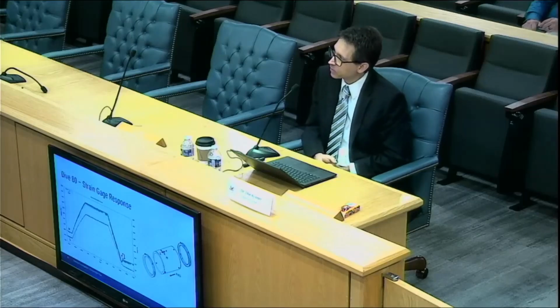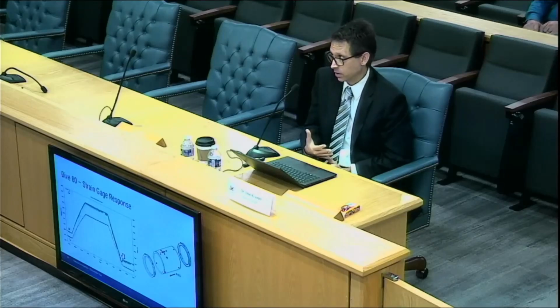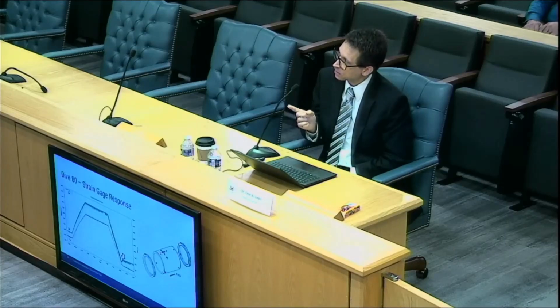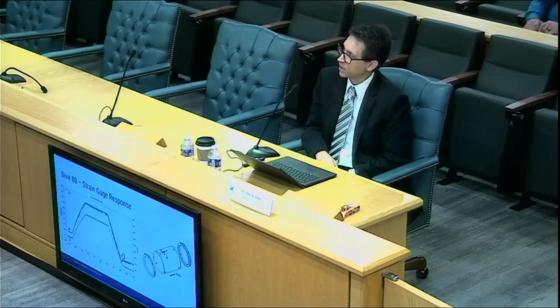So it means that there is a sudden change in both the longitudinal and the hoop strain at this particular location of the hull. And we see this type of response for this gauge group 4, and we don't see it for other gauge groups, such as group 3. And so there's a change in the strain in the hull that is occurring at this location that is not occurring at other locations.